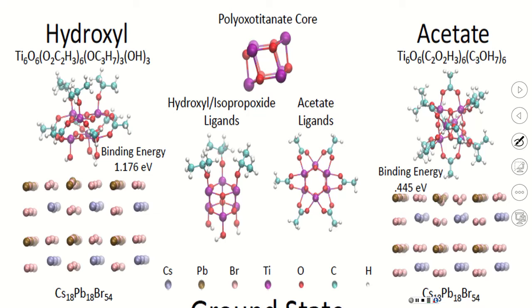And there are also dual ligands, isopropoxide and, first is hydroxyl, second is acetate, right? So then if one wants to facilitate charge transfer, these ligands will be isolated. They will not allow charge transfer. So therefore, in order to facilitate charge transfer, one can pull off a ligand, but for chemical stoichiometry, put the simplest possible ligand like hydroxyl, and then smash the surface into perovskite. This is kind of too many technical details, but it is a good mimic of what is going on in an experiment.